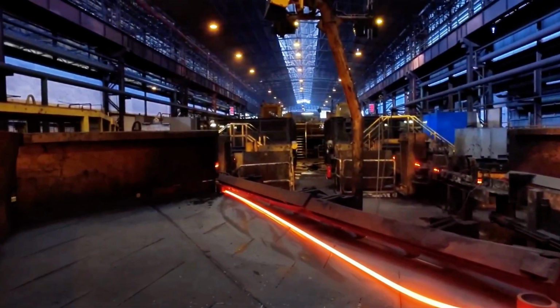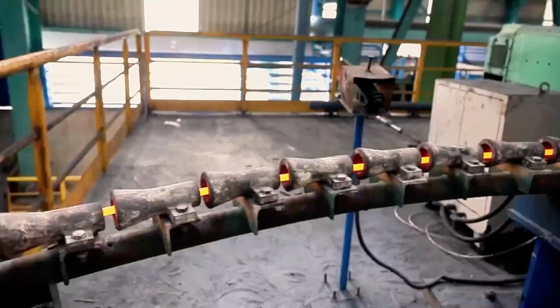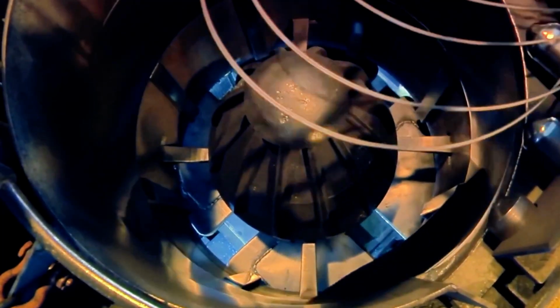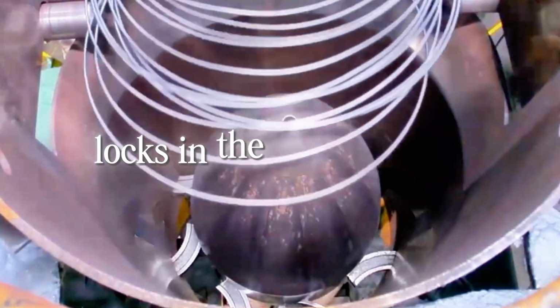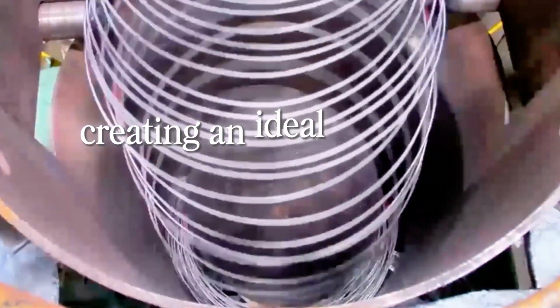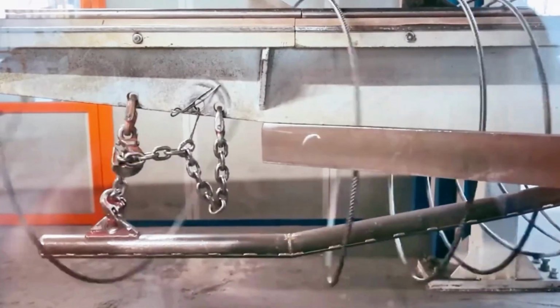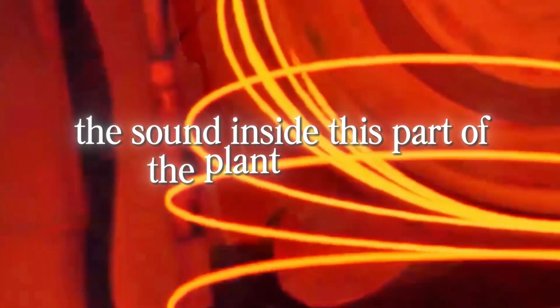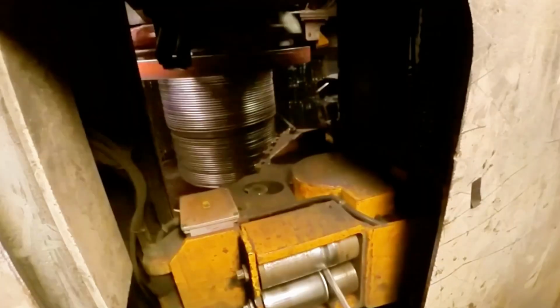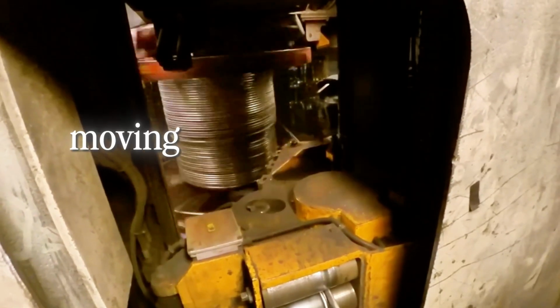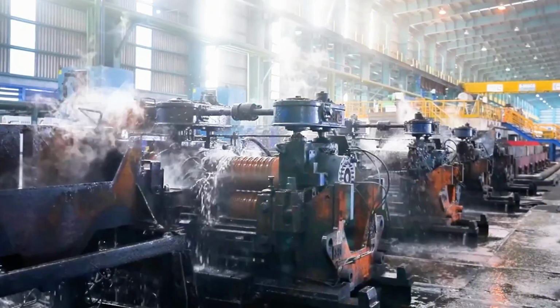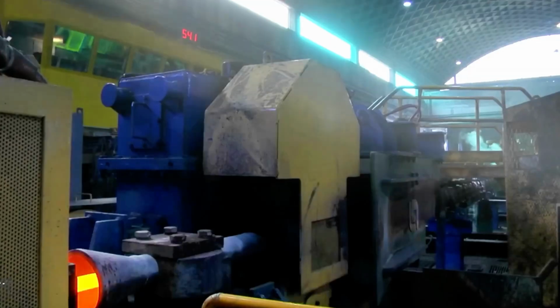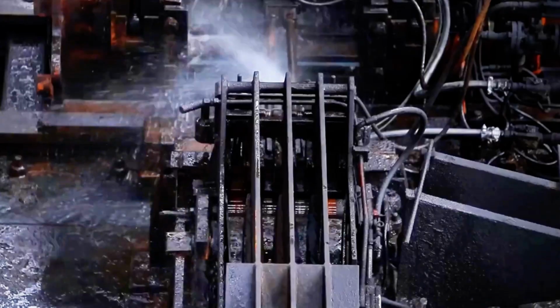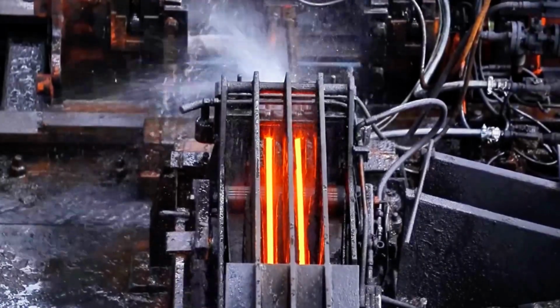Once the right temperature is reached, the wire is rapidly cooled using high-pressure air or oil in a process known as quenching. This sudden drop in temperature locks in the new structure, creating an ideal balance of strength and ductility. The sound inside this part of the plant is surreal, a mix of hissing air, roaring furnaces, and the steady hum of conveyor lines moving miles of glowing steel. By the time the coils emerge, they've transformed again. No longer raw metal, but precision-engineered filaments of strength.